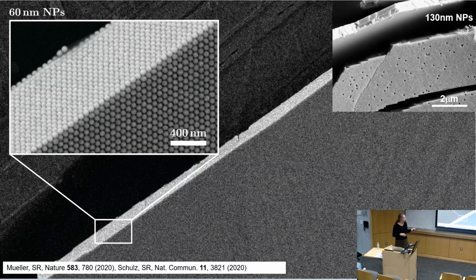Yeah, so this now is an SEM image where you see a little lamella of such a gold nanoparticle crystal. And if you look at the edge, you see the two facets of 111, with their characteristic hexagonal close packing. This was for 60 nanometer gold nanoparticles. By now, he increased the size of the nanoparticles to 130 nanometers, and they can still crystallize in these beautiful supercrystals.